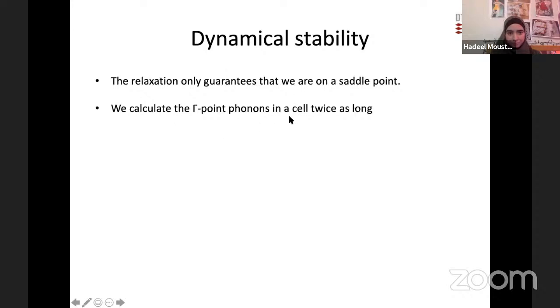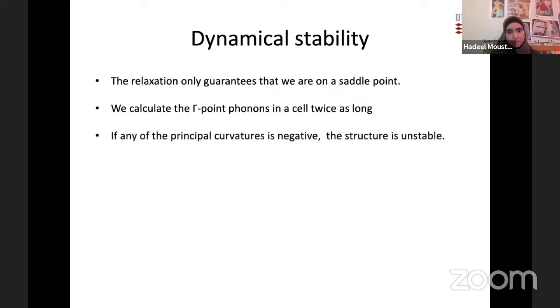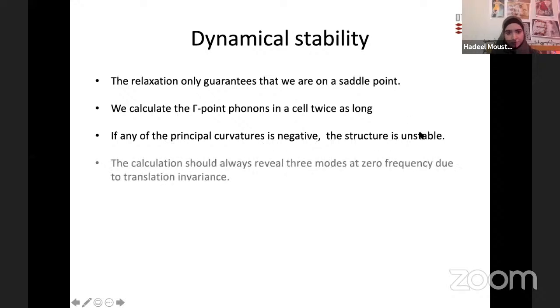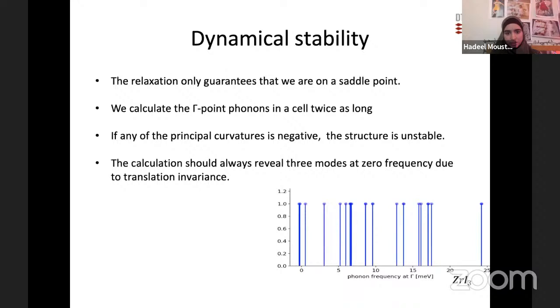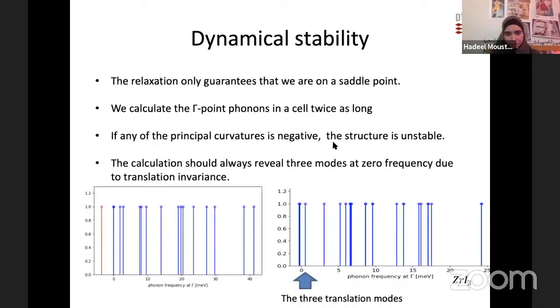And for that, we calculated the forces, which represent the curvature of the potential energy surface. And if the principal curvature is negative, then the structure is unstable. And here I have two materials. This one is stable and this one is unstable. And here we have the three translation modes.